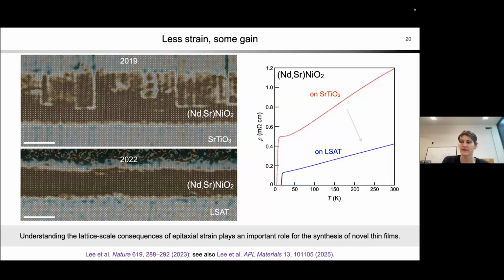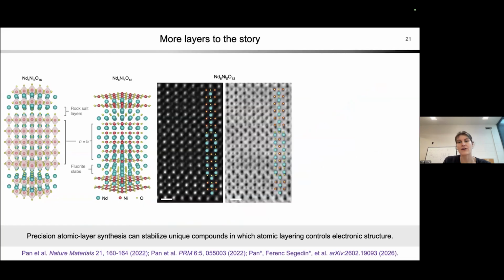So over the past about 5 to 6 years, we've been in this ongoing cycle of optimizing the synthesis of these materials and readdressing scientific questions. Everything I've shown you so far is these neodymium nickelate materials, strontium substituted neodymium nickelate. But it turns out that just like the cuprates, all kinds of chemistries work. You can use different rare earths: lanthanum, praseodymium, or samarium. You can use strontium, calcium, europium. And actually, you don't even need to dope the films. You can do structural variations.